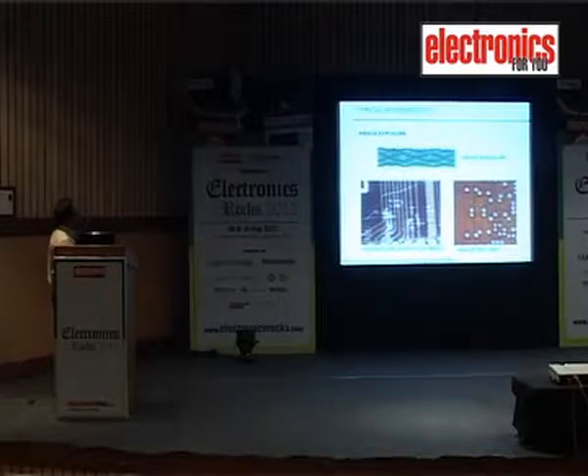And if you see, these are the weave structures where glass fibers are laid and to which resin has been applied. So what happens is, when the laminate material is handled improperly, or if it is subjected to higher thermal stress, there will be a detachment of the glass fibers at the intersection of the glass fibers from the resin, and it makes a dot or a cross, which we call measling, and the continuous structure or chain of measling we call crazing.